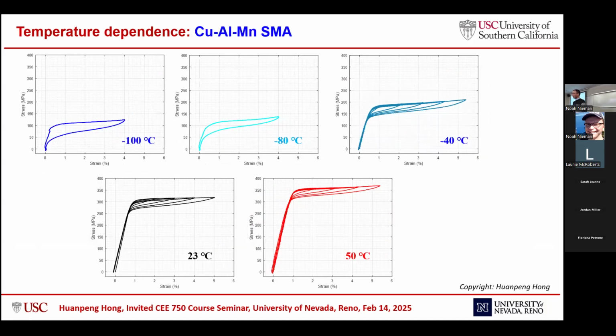Here comes the copper aluminum manganese shape memory alloy. The rest of the setup is the same. This material behaves really well at minus 40 Celsius, room temperature, and 50 Celsius.